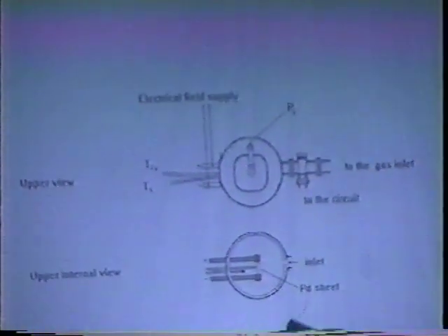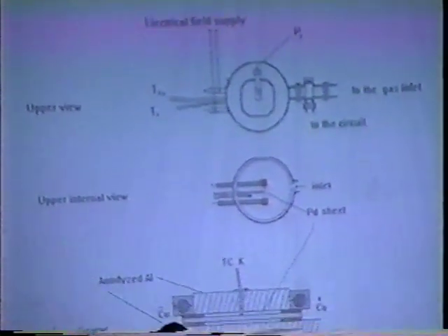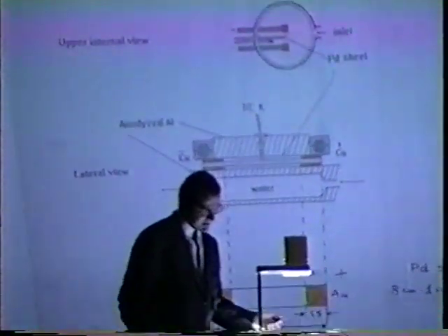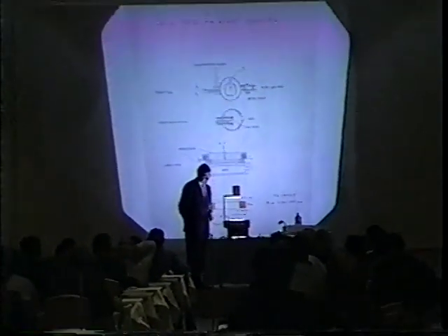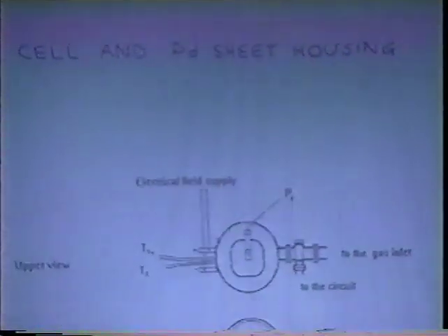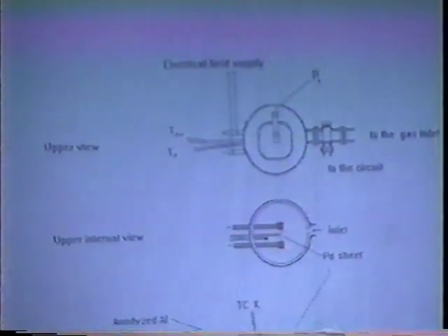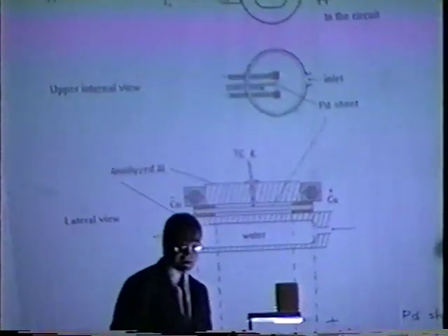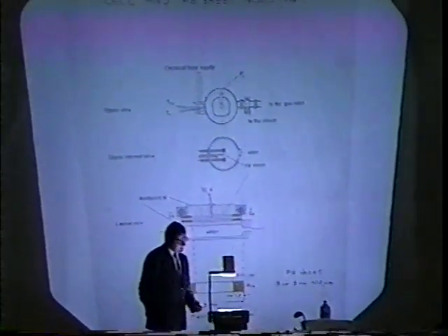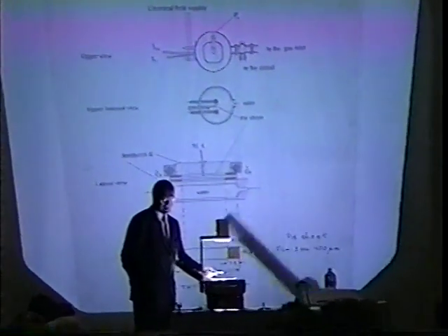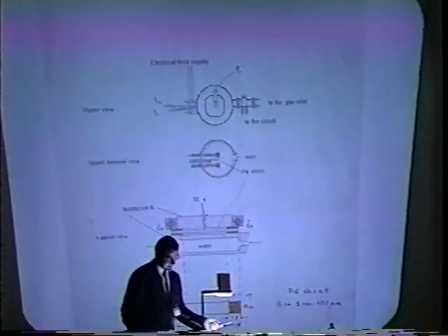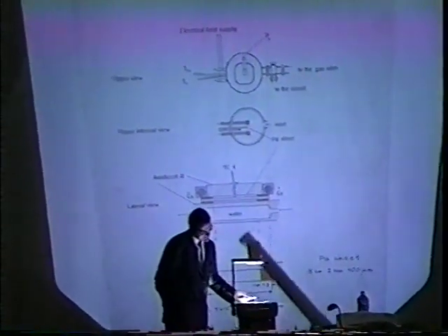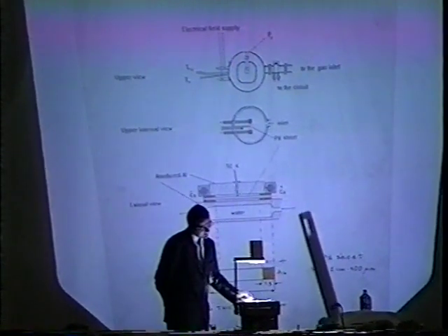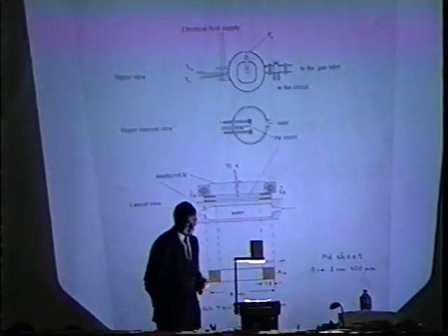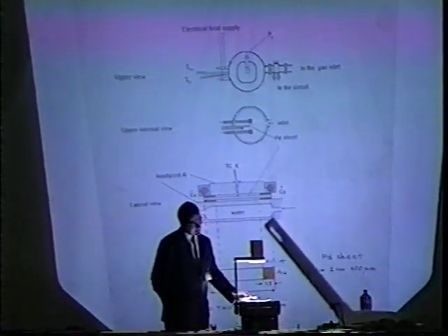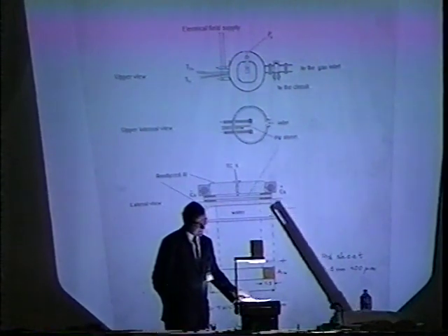The Pd sample is located on the bottom of the cell, and its mean temperature is read by a thermocouple during the run without the applied electrical fields. The cell is completely machined in stainless steel, except for the lower side, the bottom, which is made of anodized aluminum in order to ensure the electrical insulation between the sample and the cell. Down the bottom of the cell, we have a chamber allowing the flow of cooling water in order to remove the heat due to Joule effect that we have when we apply the electrical field to the sample.